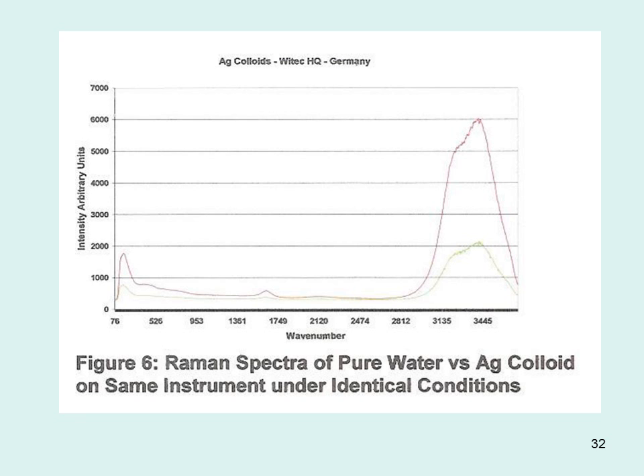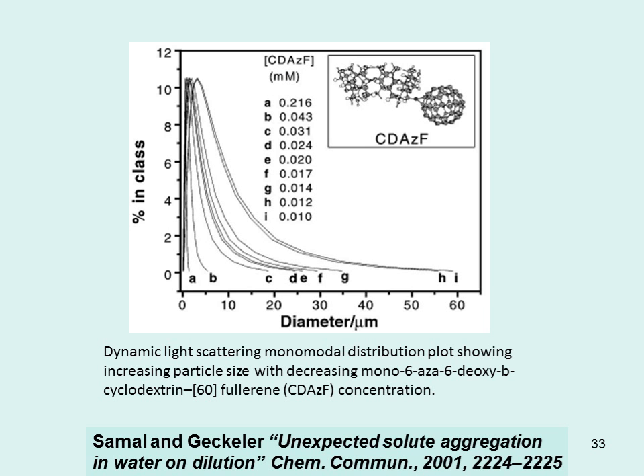And we looked at the same thing: are these structures different? This is done not with the same instrument, therefore you see the lack of resolution at the 3445 peaks, because this is a different geometry. That is an immersion laser, and this is done from outside. But by and large, again, a changed Raman spectrum for the silver balls.